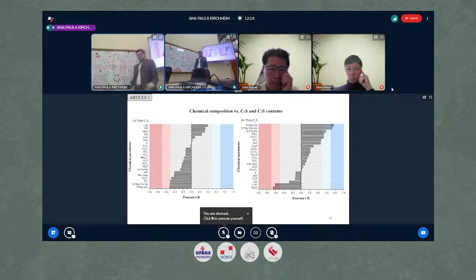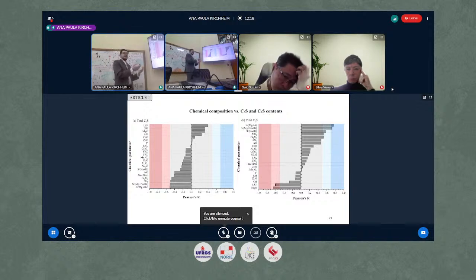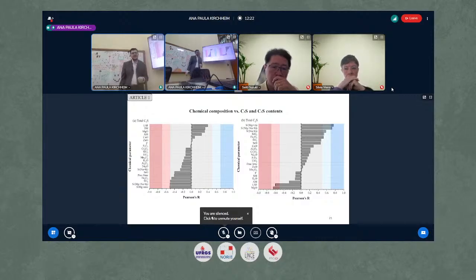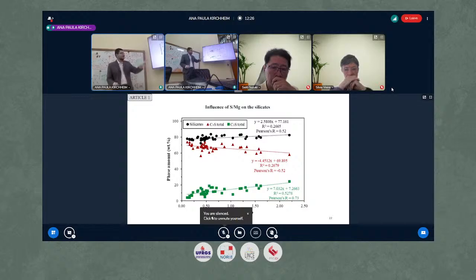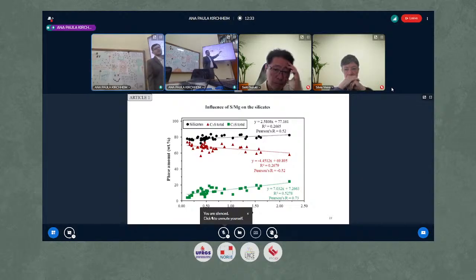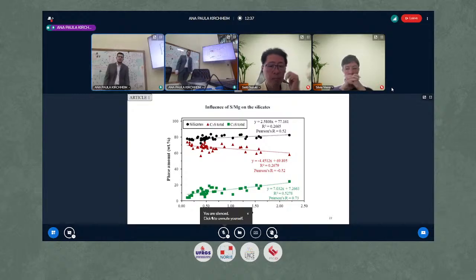So here we see the influence of minor elements instead of the four main ones. Magnesium and sulfate have a great impact on alite and belite content. And here we see clearly that sulfate favors belite, while magnesium favors alite. This is also according to the literature.